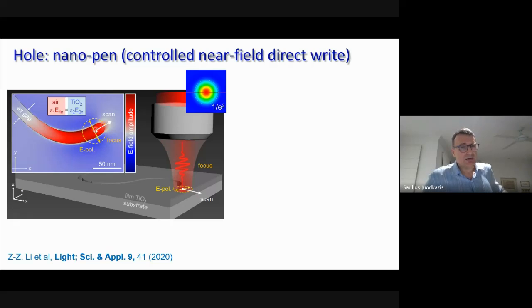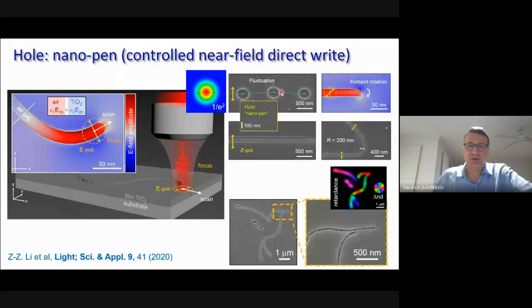So 10 times and more intensity difference can be in the gap, and we calculate this for an interface, but the gap is very small. So light is kind of counterintuitively squeezed into the low intensity region. It's not wave guiding, it's near field. So this light is not propagating, but it's really focused in the near field. And what we can do with this light, we ablate a spot, as I showed in mask writing for solar cells. It's a big hole. It still can be subdiffraction limited, but it's a large object.